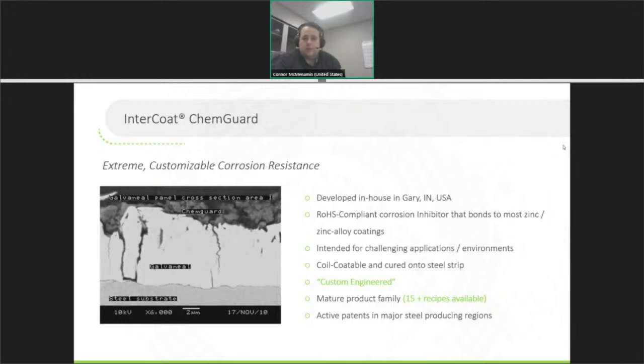We coat this currently exclusively on our line, but are branching out. And the photo to the left that I want to point out is a scanning electron microscope image illustrating our coating over galvannealed. If it's not quite large enough, I suppose, but if you look at it, you can see that it's getting into all the pores in the galvannealed coating, which I believe is an A25 or A40, which really helps lock in a very strong, let's call it corrosion inhibition. We call it a zinc life extender over here.